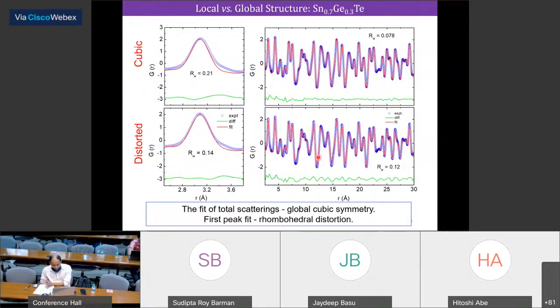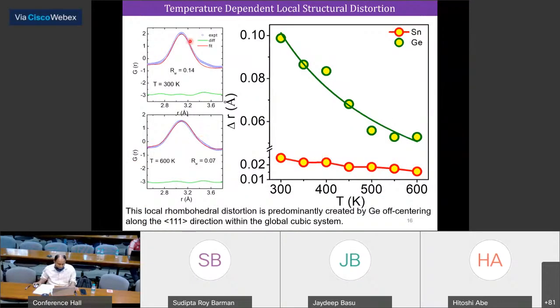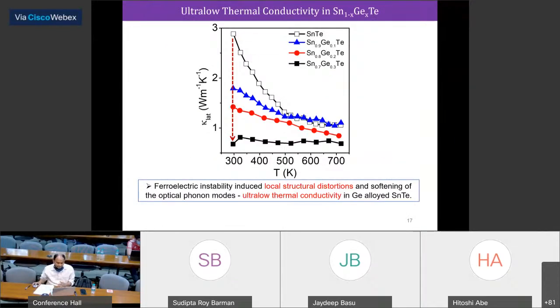And we have done the temperature dependent PDF, which shows that germanium is distorted 0.1 angstrom locally, which is quite big in terms of a bond length, and the distortion remains above TC. So that means this local distortion actually creates this ferroelectric instability in rock salt tin telluride and gives rise to low energy optical phonon modes, which scatter the heat carrying acoustic phonon mode. And that's why we measured very, very low lattice thermal conductivity. That was the record low value in tin telluride thermoelectrics.